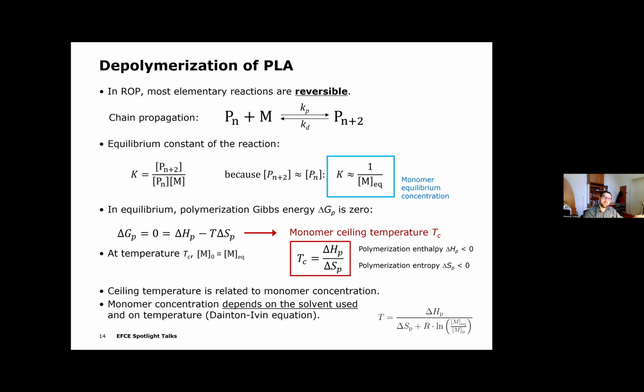If we write down the equilibrium constant of this reaction and assume that the concentration of the active chains doesn't depend on their chain length, we get this classical formula that the equilibrium constant of this reaction is inversely proportional to the so-called monomer equilibrium concentration. What does it mean? In equilibrium, as we know from this famous thermodynamic formula, the Gibbs energy of the reaction is 0.